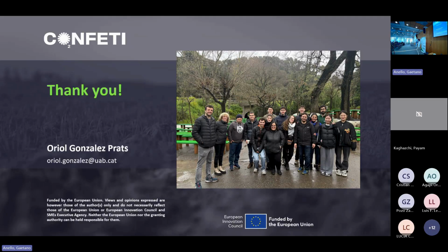I have a question. You have a champion ionic liquid, but maybe I missed why this ionic liquid is the best. This is a question that we have in the group because we don't know why. We just tested, and for this material, we had more or less the same capture in the ionic liquid, and we don't know why when we introduce this material in a solid support there is this significant change between the capture in the ionic liquid and in the material. This is something we don't have the answer to. But you did some spectroscopy or something like this to see if anything chemically changed?